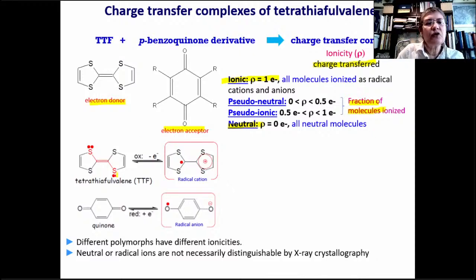So both donor and acceptor form radical ions. So tetrathiafulvalene forms this radical cation, and the quinones form radical anions. But it also happens that their charge transfer is not necessarily obvious by X-ray crystallography. And different polymorphs of the products can have different ionicities.